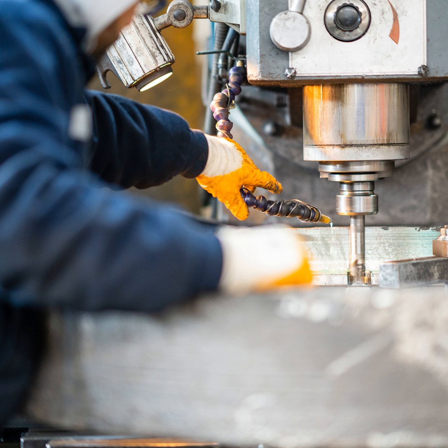And if we see how tools normally wear, we don't live in a perfect world. These tools typically chip away, and very seldom do we see even wear throughout the cutting edges. So we really have picked up an essential component with added ductility. This allows us to be a little bit more aggressive with the cutting edges because we do have increased ductility. Because of the fine grain structure, it also allows us to manipulate the edges when it comes to edge prep.